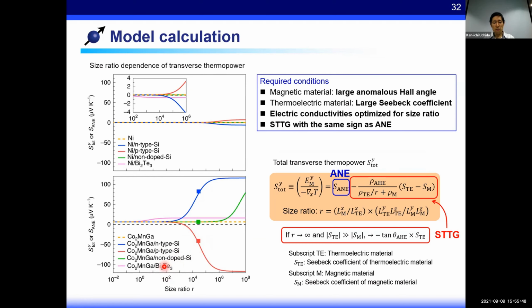Bismuth telluride is one of the best thermoelectric materials at room temperature. However, the Seebeck coefficient of bismuth telluride is smaller than silicon, so the saturation value of this pink line is much smaller than the case of silicon. However, the electrical conductivity of bismuth telluride is much better than silicon, so we can obtain relatively large STTG thermopower even at small size ratio. A small size ratio means that the volume of the thermoelectric materials can be reduced, so it's convenient for improving the efficiency. So can I answer you?